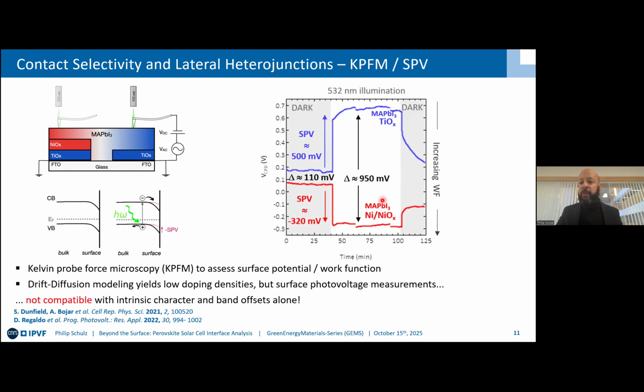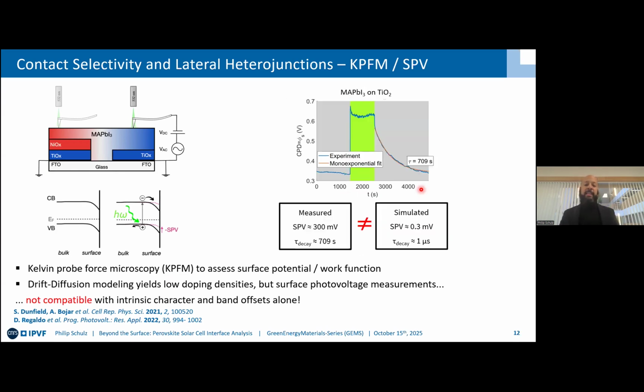You can also see that once you turn off the light, it does not return to its initial value. So that also tests that it's not a purely electronic effect. And indeed, once you look into this decay and compare it to what you get in a drift diffusion model, you are off in terms of first magnitude of the surface photovoltage, but then also in the decay time by here it's 3 orders of magnitude, or even 5 orders of magnitude in terms of the time. Actually, even more, 8. So with this, we also need to consider deep defects at the interface.